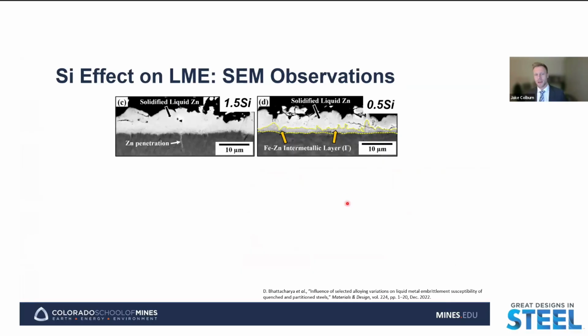If we want to look more deeply into why we're seeing the differences in this behavior, we can start by looking at some SEM images of the cross-section of the hot tension samples after testing at 700 degrees C. Here we have backscatter electron images, where the contrast is related to the atomic number of the elements we're looking at. Zinc, having the highest atomic number of the elements we're looking at, will appear with the lightest contrast. So when we have those regions of zinc that have alloyed some with iron, we're going to see a darker contrast.